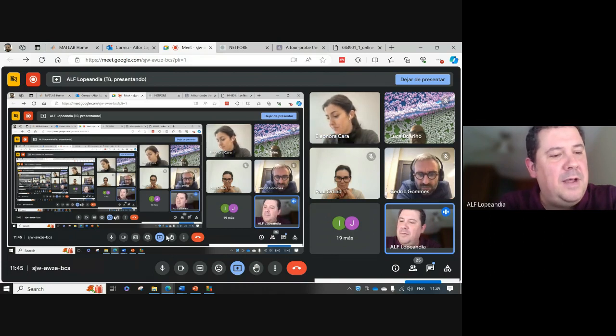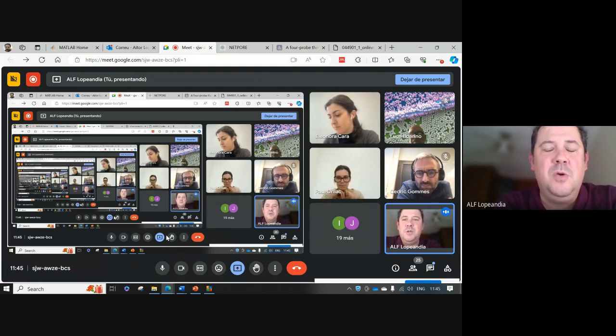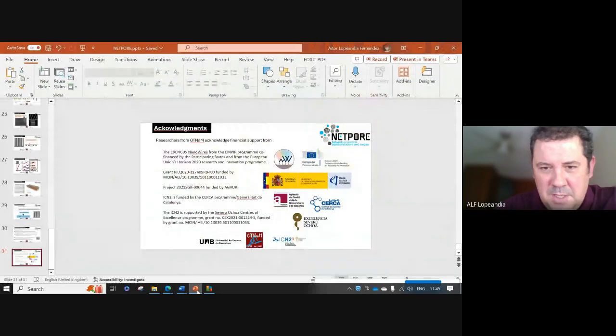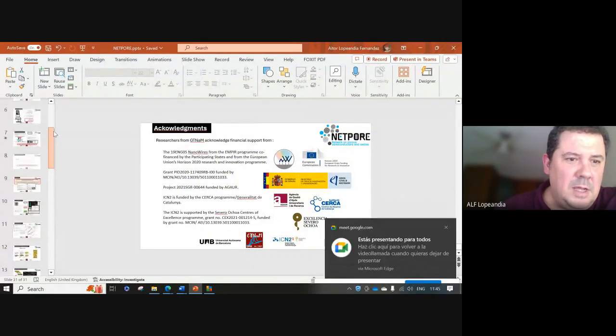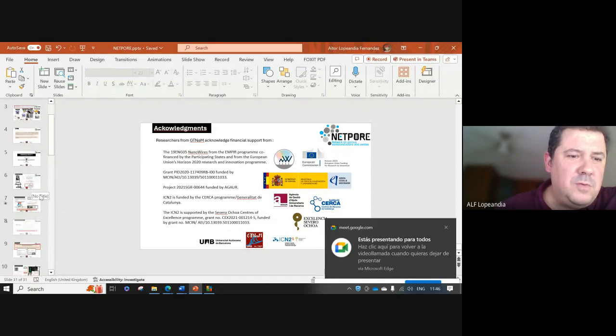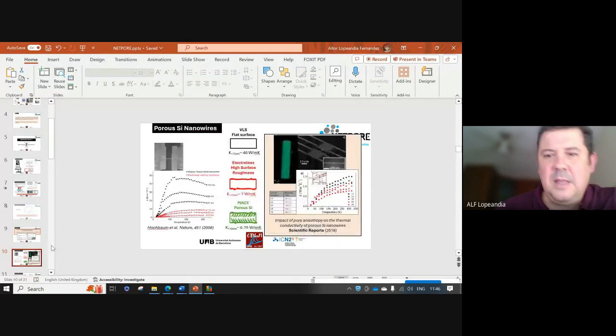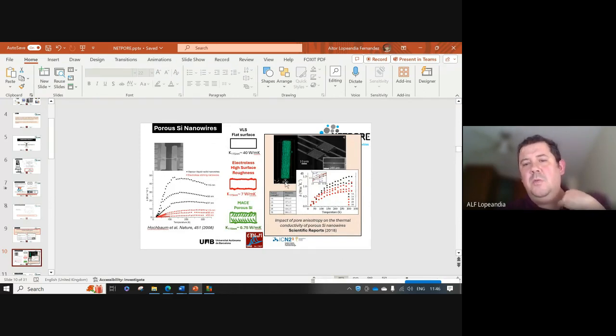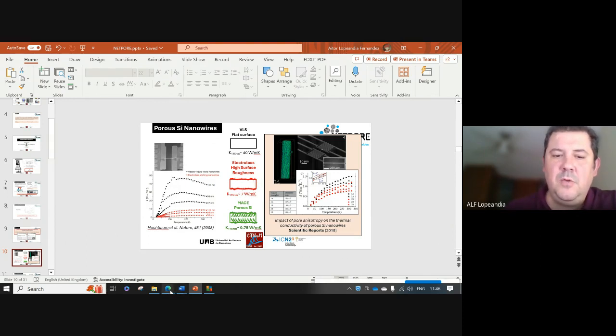Essentially because the pores act as scattering points for the mean free path of the phonons. In the nanowires that we show in the article, the thermal conductivity we got was really close to the amorphous limit, and that was essentially because all the porous structure was acting as a scattering for the main phonons that used to drive heat in silicon. I don't know if I answered your question.